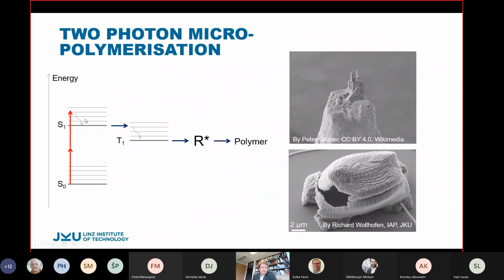When we look at the Jablonski diagram, usually what is used is a negative-tone radical polymer. In most cases, it's acrylates or methacrylates. You need a starter, and the starter absorbs 2 photons, transfers to the triplet state, and from the triplet state you go to a radical, and that induces the polymerization of the acrylates or the thiol-ene or whatever you have.